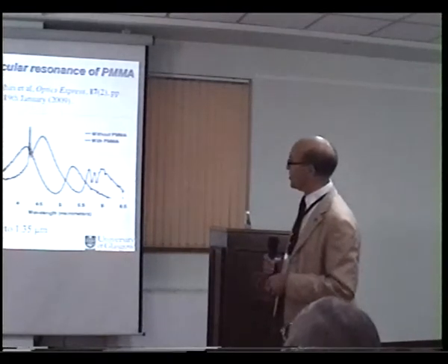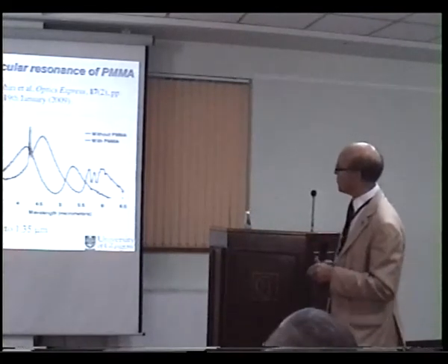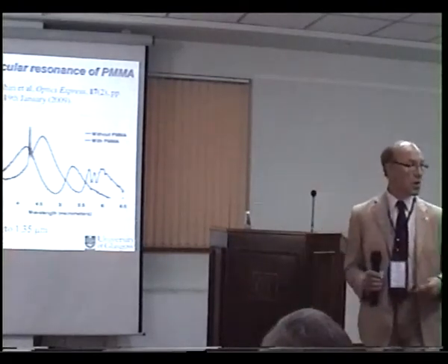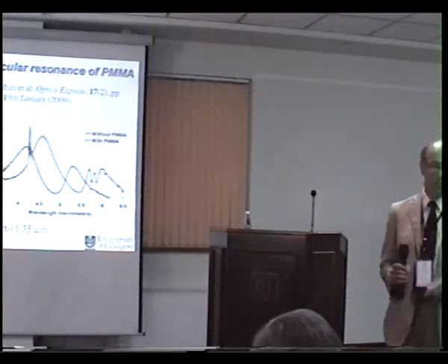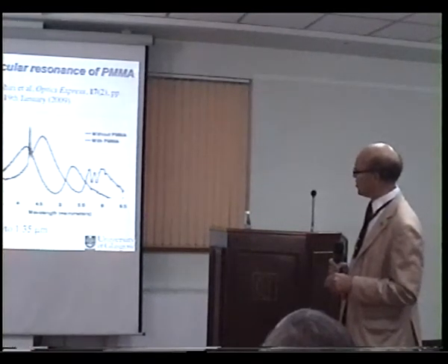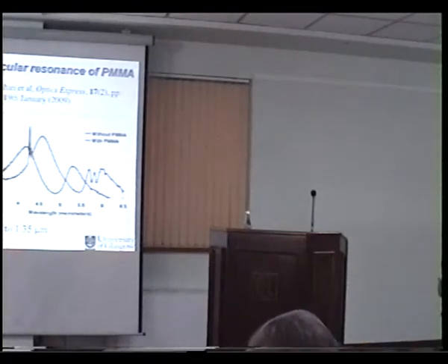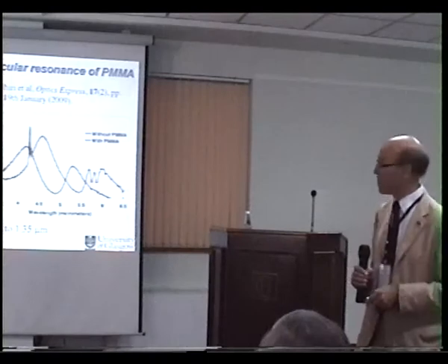So I put down polymethyl methacrylate, PMMA, on top. I get this curve here, the red curve. I get a reflection peak which is shifted simply because I've changed the refractive index above the structure. I've changed the refractive index, so I shift the resonance. So I shift this reflection peak across, I shift the dip across. That feature in there is a spectral feature just of the atmosphere. It is at a wavelength above 4 micrometers, so it's probably the presence of CO2 in the atmosphere, which is important.